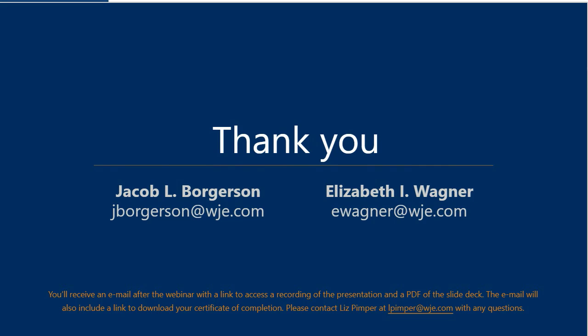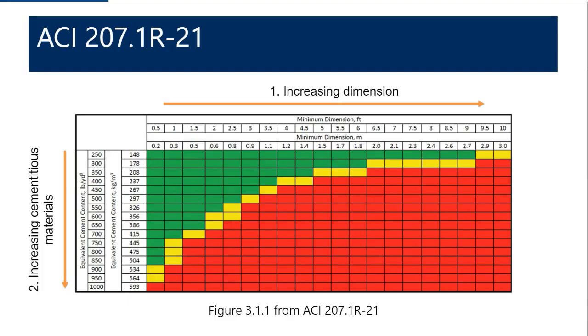All right, so this is actually a question that I meant to clarify before and did not, so I'm glad it was asked. So in this graph from ACI 207.1, it talks about equivalent cement content. So I've been using the term cementitious content, but really I should be talking about the equivalent cement content. Cementitious content is going to include the cement and SCMs like fly ash and slag, but the equivalent cement content is actually going to essentially be related to the contributions of those different components to the heat generation.